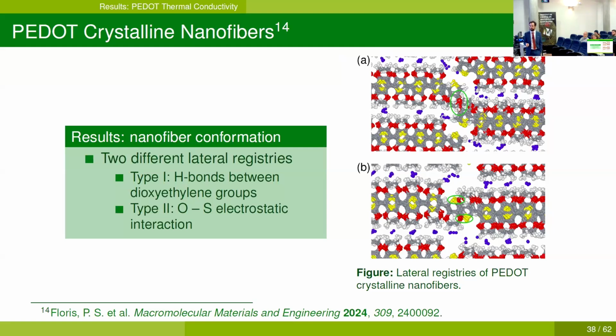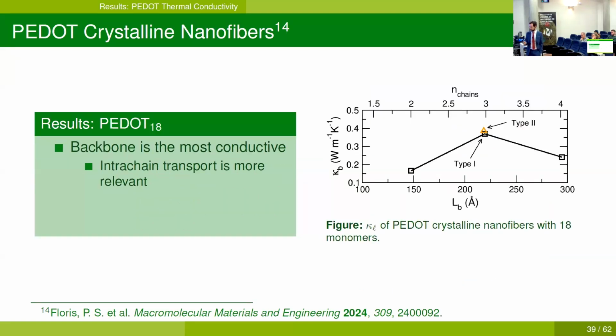chains. And we couldn't reliably define a protocol to generate either type 1 or type 2 lateral registry. This appears to be just a chaotic phenomenon, and it depends heavily on the initial positions of the atoms when we do the replication. And it appears that type 2 produces higher thermal conductivity. We can also see that here, where type 2 is slightly higher than type 1.